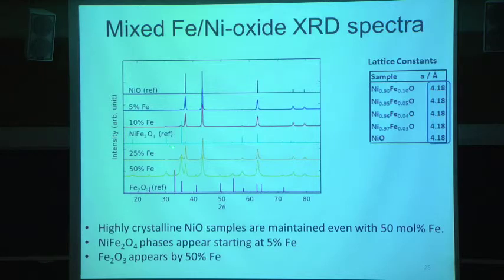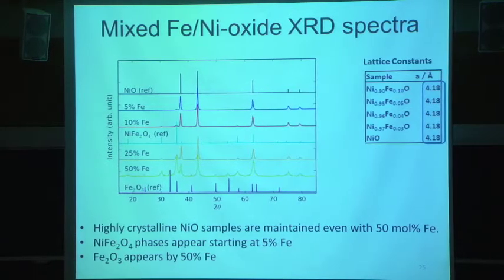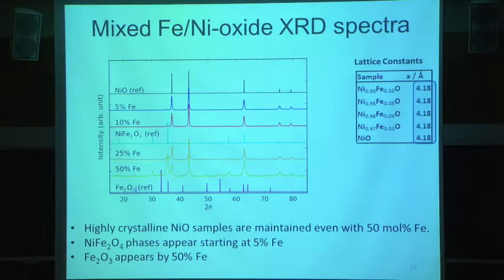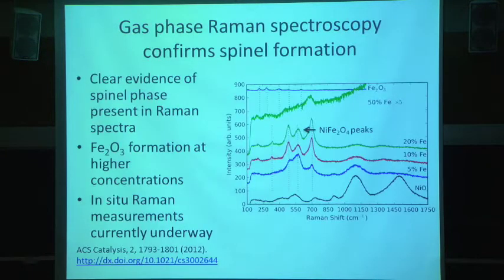And what you start to see, as you get to about 25% iron, is formation of this nickel iron 2 spinel phase. So this phase starts to appear already in the 10%, and it grows. And then once you get to 50%, you start seeing very clear indications of Fe2O3. And we know Fe2O3 is a terrible electrocatalyst. So it's conceivable that we have the spinel phase that's forming, and that is a possible way to promote the nickel oxide samples. We see evidence of the spinel phase in the Raman spectroscopy.